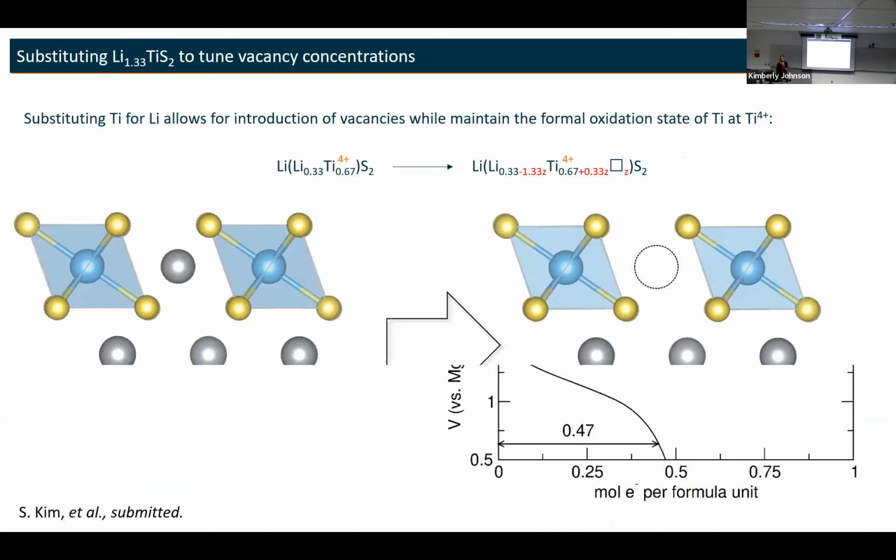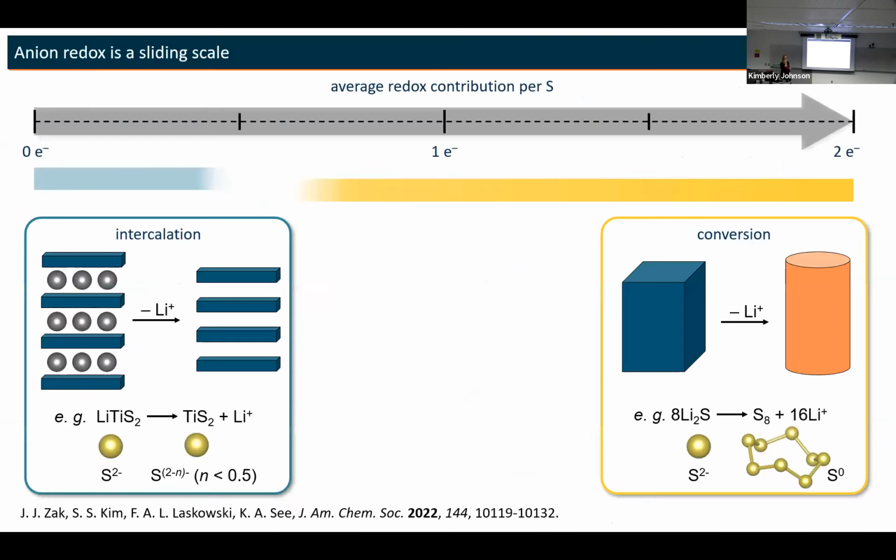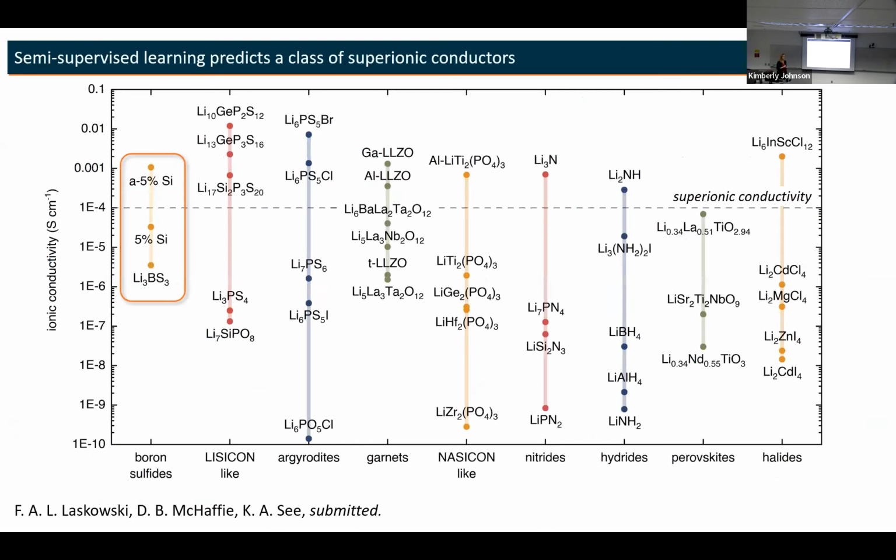The nice thing about lithium is that you can do atomic characterization using nuclear magnetic resonance, NMR. So you can figure out what the diffusivity is that way, and that'll give you a really nice probe of how the lithium is actually moving. But all of these materials here are pretty wide bandgap materials that don't have a high electronic contribution. So the electronic contribution is like 5 orders of magnitude lower than the ionic. So then we just don't care about it.